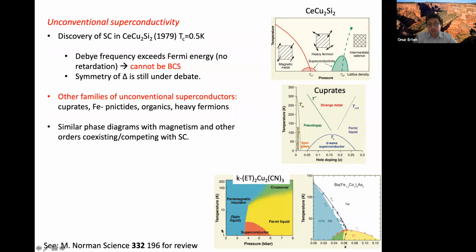And in the case of organic salts, this does not really show any long-range order, so they write spin liquid. And as a function of some tuning parameter, this magnetic order is suppressed. Here, here, here, and in this case, pressure here. And when you suppress this magnetic order, you have superconductivity. And of course, there are a lot of material-specific phenomena, which I'm not discussing here. Cuprates has its own controversies on pseudo-gap, strange metal, which again, I'm not going to go into details of. I'm mostly going to talk about superconductivity.